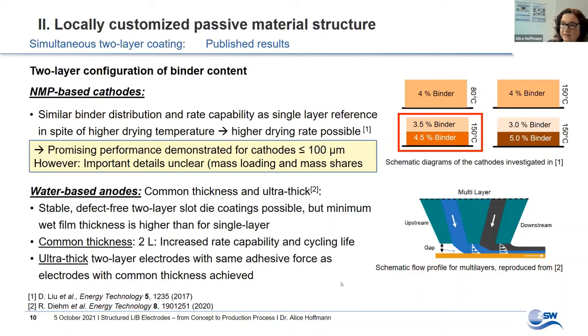However, also in this study, the coatings or the layers were tuned to the same wet film thickness, although the solid contents and the active material proportion in the slurries were different. So in this case, it is not clear how much active material is in which layer. So I will show experiments that try to address this issue.